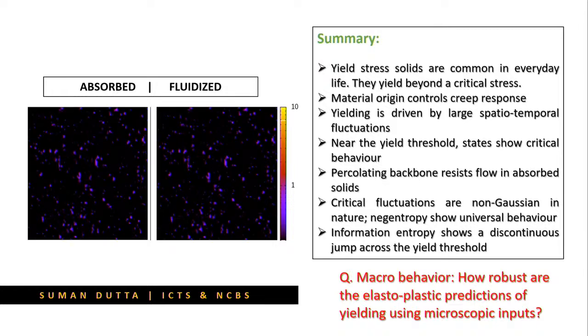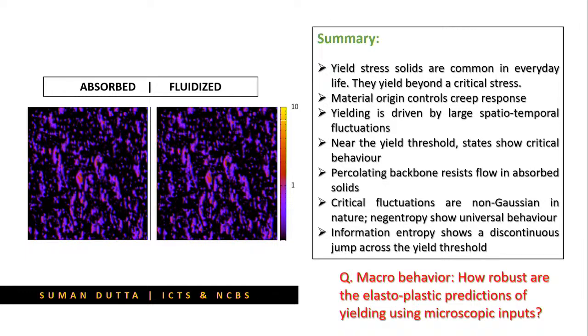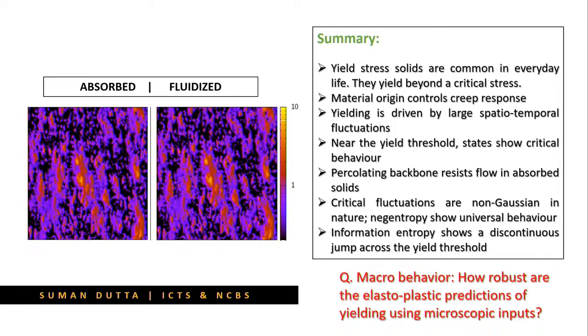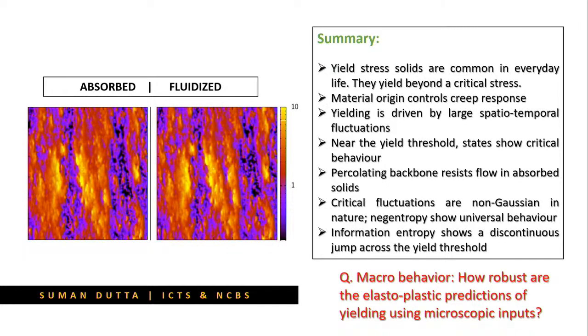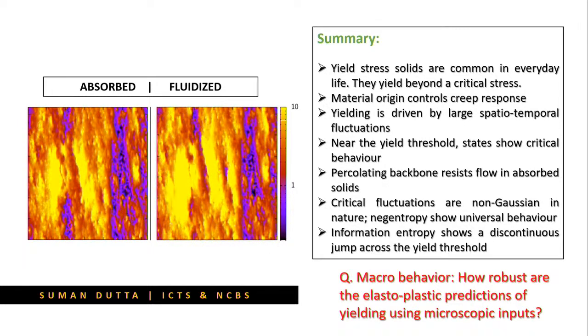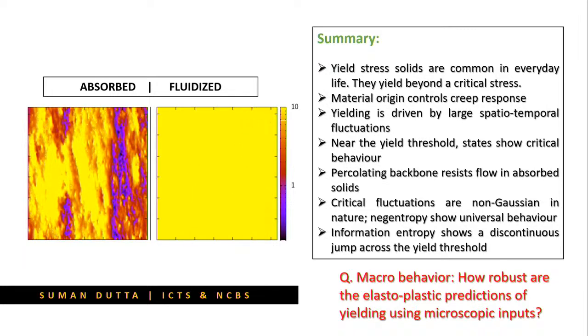When it flows, there is a dilation of the backbone, and when it does not flow, it remains in the absorbing state. The critical fluctuations associated with yielding are non-Gaussian in nature, and the non-Gaussianity measure that we deal with, the negentropy, shows some indication of universal behavior near the threshold. The informational entropy approach that we have shown shows a discontinuous jump across the yield threshold. So, this is the work that was ongoing, and we are communicating this work. Out of this microscopic information, a simple question comes: what emerging macroscopic picture do we have, and how do we understand it?